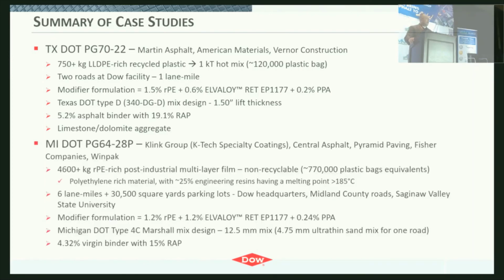In Michigan, the Klink Group produced the binder, Central Asphalt and Pyramid Paving did the hot mix, Fisher Companies did the construction. Winpak, which is a Dow customer, supplied the recycled material. This was a little bit different than what we did in Texas. This was a post-industrial recycled material, so industrial scrap. It was also a mixed stream. It was around 75% linear low density polyethylene. The remainder, around 25%, was an engineered polymer with a melting point above 185 C.